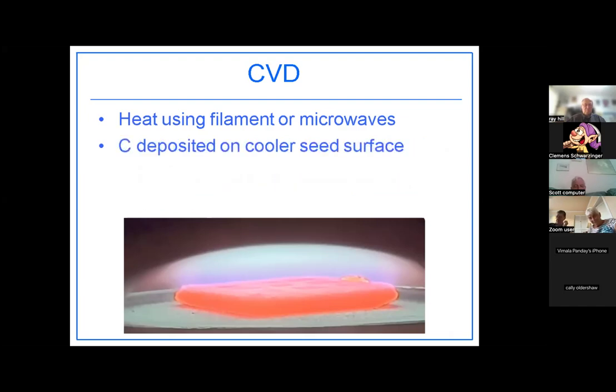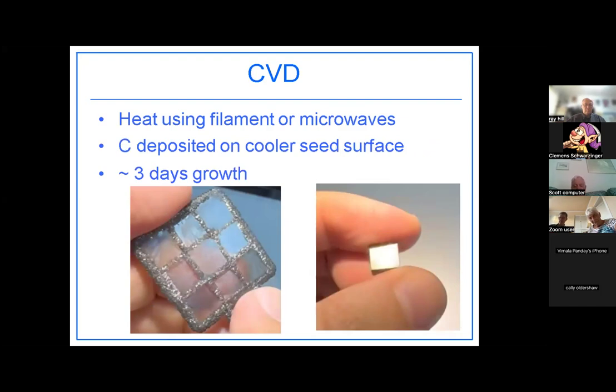And your carbon is deposited on the cooler seed surface, and this is what you look at after 3 days of growth. So on the left-hand picture, you see the graphitization of the carbon. But where the crystals are, you get your diamond deposited. And on the right-hand picture, you have your crystal of CVD grown diamond.